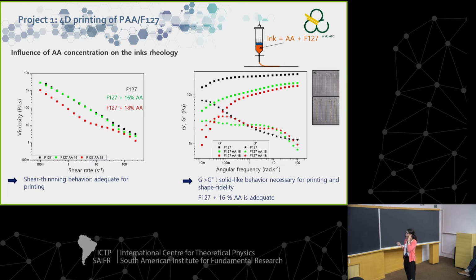And then we look at the frequency sweep test, which measures the storage modulus and the loss modulus. We want the storage modulus, which are the squares, to be higher than the loss modulus, which are the stars. This is the case in pure Pluronic and in the one with 16% acrylic acid, but not with 18% acrylic acid. So it seems that 16% acrylic acid is more adequate for printing.